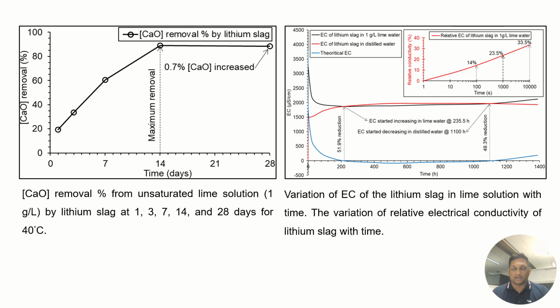Lithium slag is highly efficient, consuming 19.4% lime in 1 day, followed by 88.9% lime removal at 28 days, which fulfills the requirement of British Standard 8615. Little calcium oxide concentration increased at 28 days due to atmospheric carbon dioxide precipitation to form calcium carbonate by reacting with calcium hydroxide.